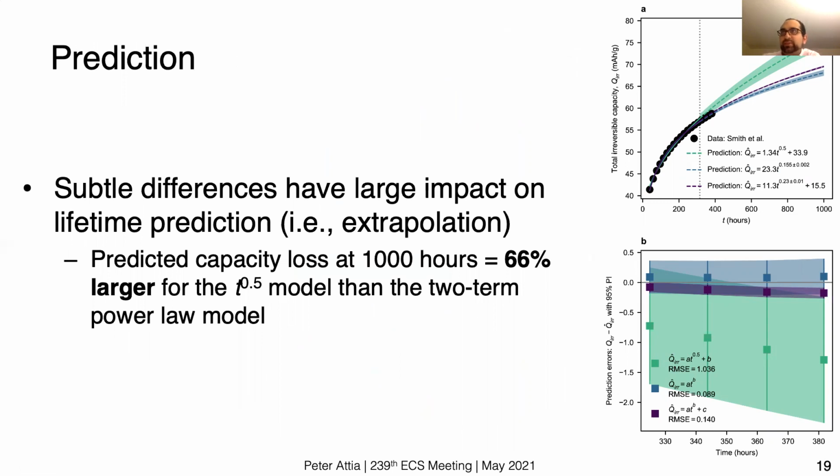What we did here is we took this Smith et al. data set, again, another UHPC data set, and we fit the data to the first 15 out of 19 data points in this trend and looked at the error for the remaining 4. So this is sort of simulating what we would be doing if we were extrapolating. But instead, we're looking at less data and seeing how the extrapolation holds.